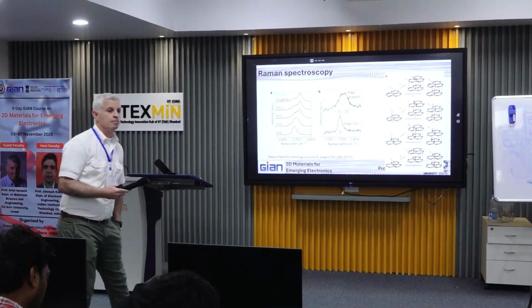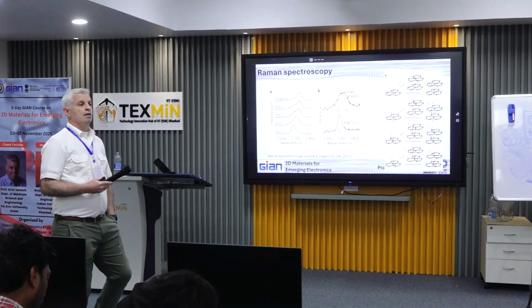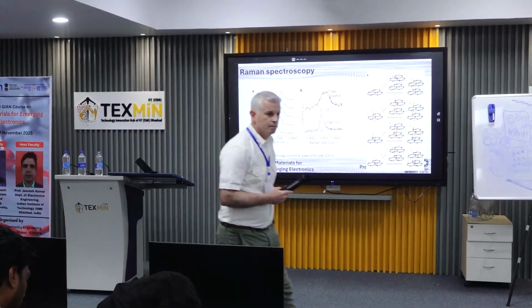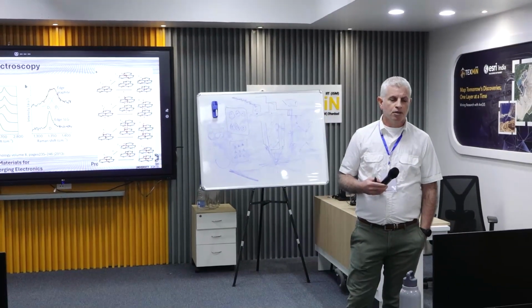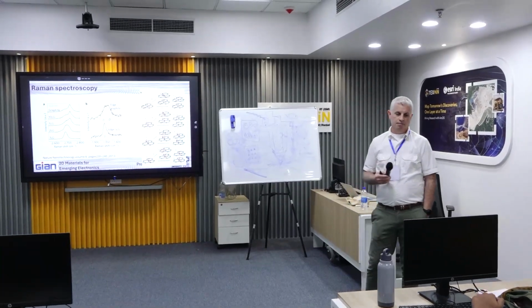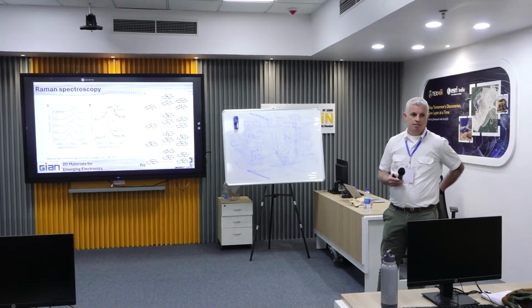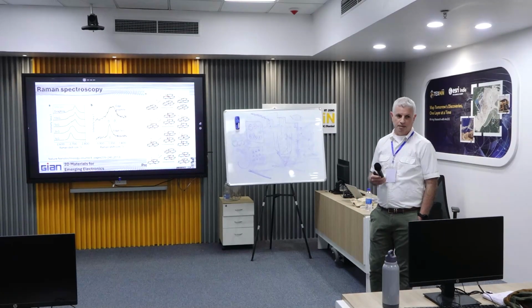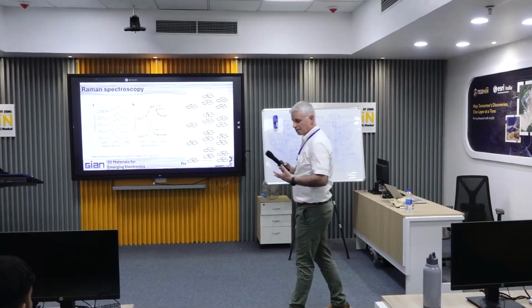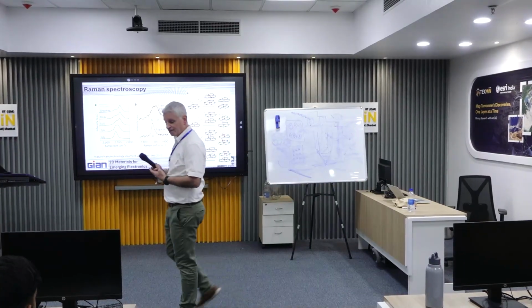Microscopic and stage, but if you use an optical microscope in that case. Optical microscope, what? Like in that case, if there are multiple single layers, can we see through an optical microscope? No, in the optical microscope, you will see a graphite, multi-layer. Only contrast you can see. In the optical microscope, you don't see any difference. Yeah, that's right. So even if you get a single layer here, then you can't find a single layer. Right. So always you need to combine different methods. Always you need to verify yourself better with different methods.